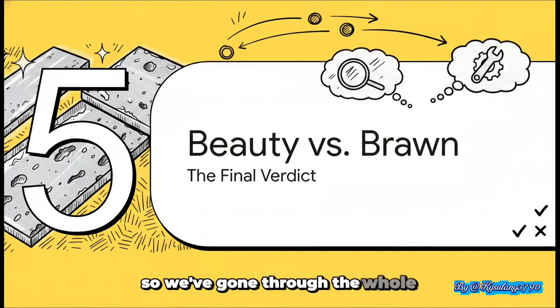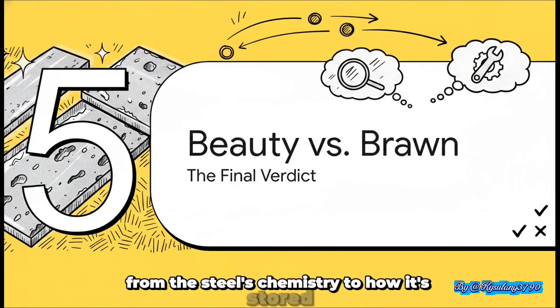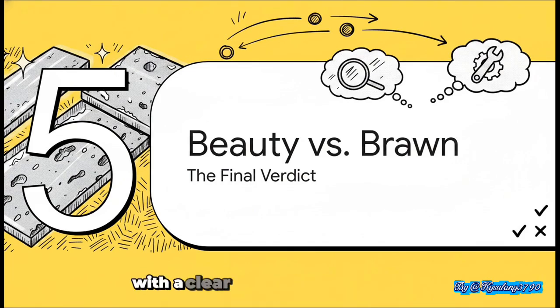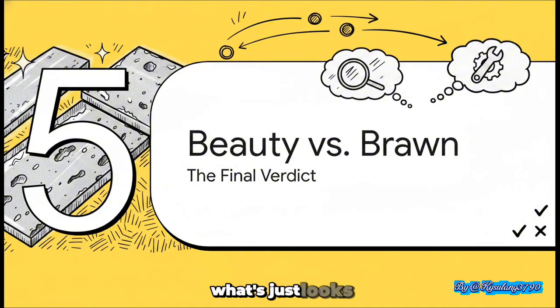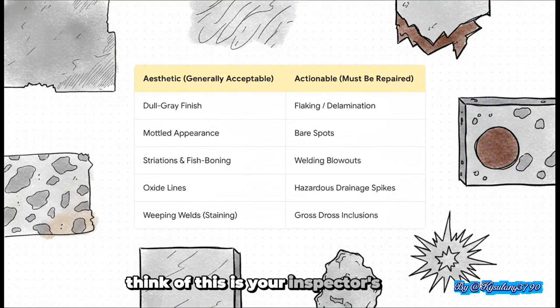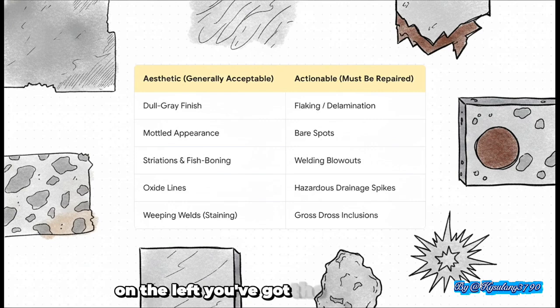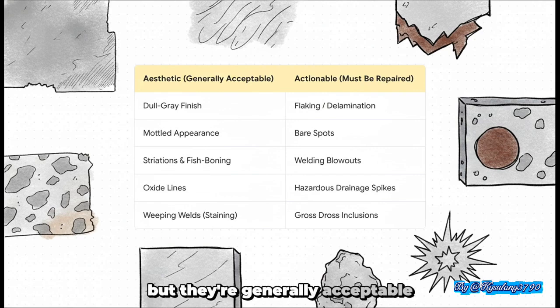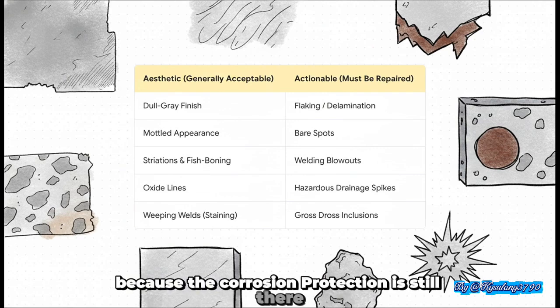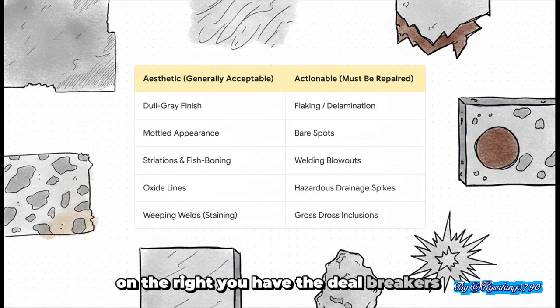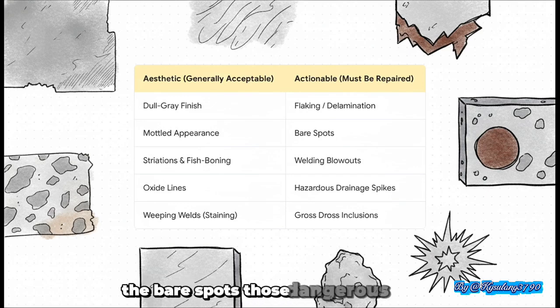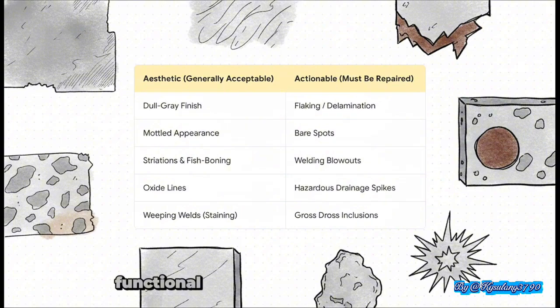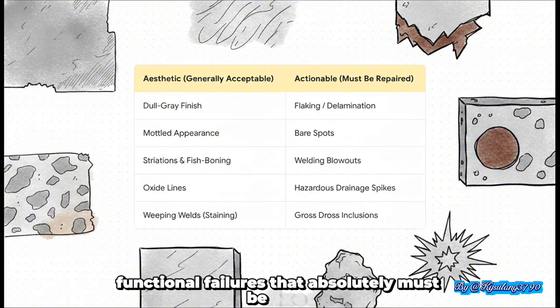So we've gone through the whole journey, from the steel's chemistry to how it's stored. Let's wrap this all up with a clear verdict on what's a real problem and what's just, well, what's just looks. Think of this as your inspector's cheat sheet. On the left, you've got the aesthetic stuff, the dull grey finish, the mottling, the stripes. They might not be pretty, but they're generally acceptable because the corrosion protection is still there. On the right, you have the deal breakers, the flaking, the bare spots, those dangerous spikes. These are real functional failures that absolutely must be fixed.